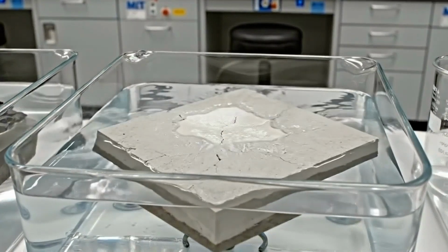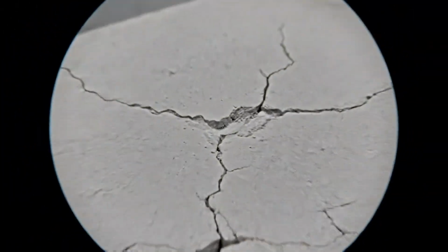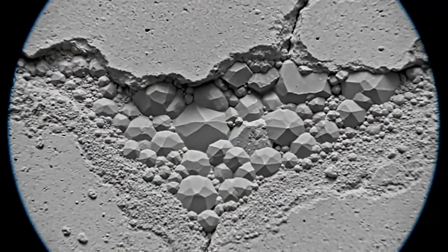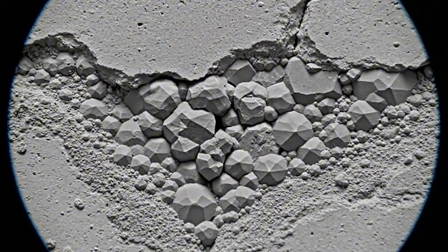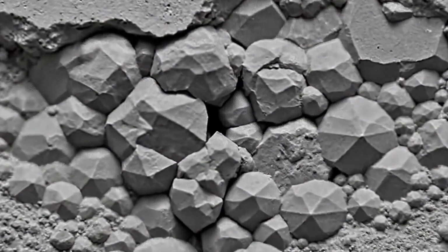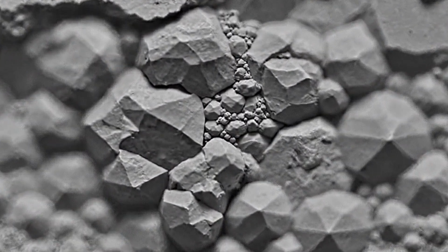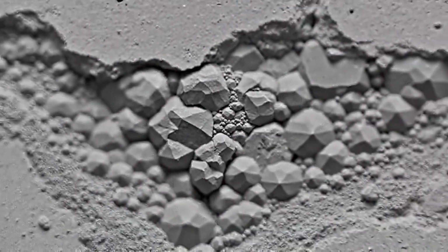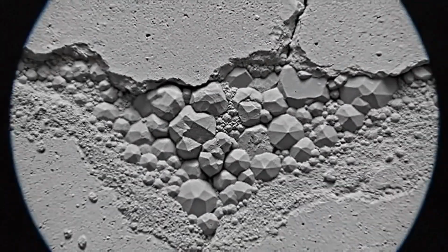Hot mixing allows the violent exothermic reaction of quicklime hydration to occur within the fresh concrete mix. The temperatures generated by this process, potentially exceeding 200 degrees Celsius at the point of reaction, created a chemical environment that cold mixing cannot replicate.